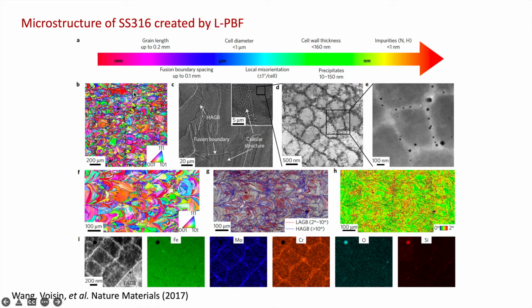At the granular level, you see many regular grain boundaries and low-angle grain boundaries. When you have a closer look into the microstructure, you see these dislocation cell walls. The cell walls are about 500 nanometers apart, and they also can behave as strong dislocation barriers. Another interesting observation is those dislocation cell walls, they have different chemical composition compared to the matrix. They are rich in moly and chromium. That is additional energy barrier to overcome when you try to deform the material.